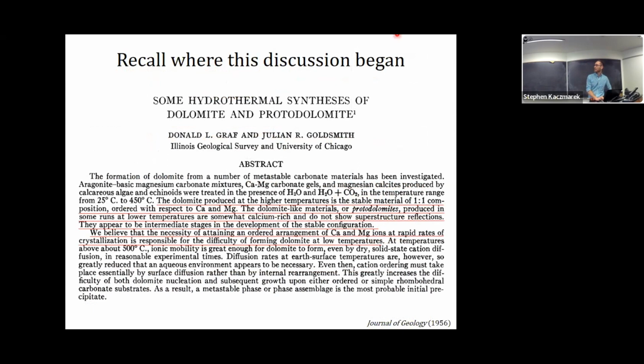Let's backtrack and remember where this began. Experiments conducted by folks in Illinois showed that at high temperature, you make ordered dolomite, and at low temperature, you make a disordered phase. Most of the data published in these low temperature microbial experiments look like they don't have the right ordering structure either, and are a mixture of hydromagnesite, aragonite, what we call protodolomite, or very high magnesium calcite.